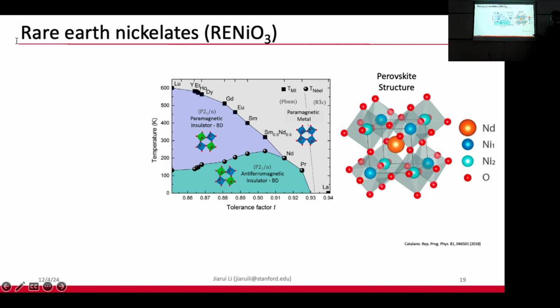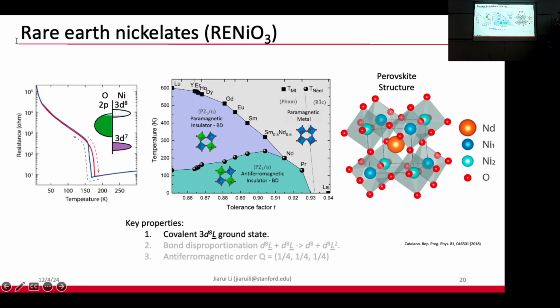There are 2 major phase transitions here. This is a phase diagram where you see that we can stuff different rare earth elements on the A site. One is the metal to insulator transition, where the resistance jumps by orders of magnitude. And the second one is a phase boundary here that separates the paramagnetic phase from the antiferromagnetic phase.